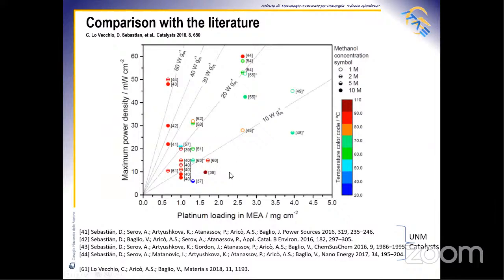Taking into account all of these discussed aspects, the Precious Group Metal free catalyst appears as a very promising formulation for cost-effective direct methanol fuel cell systems, in which platinum and all the Precious Group Metal catalysts can be completely removed from the cathode, and the low-loading platinum-ruthenium catalyst may be employed at the anode. This is summarized here, where the maximum power density is represented against the platinum content in the MEA, considering that it is only present at the anode as a platinum ruthenium catalyst.